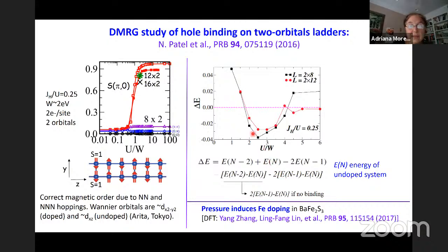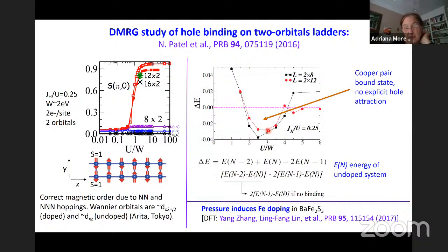What we find is that pairing is observed, but not for all values of U. It happens only in the intermediate range, corresponding to the orbital selective Mott phase. It's interesting that neither in weak coupling nor in strong coupling does this pairing occur. Again, the pairing occurs despite the fact that there is no explicit hole attraction in the Hamiltonian.